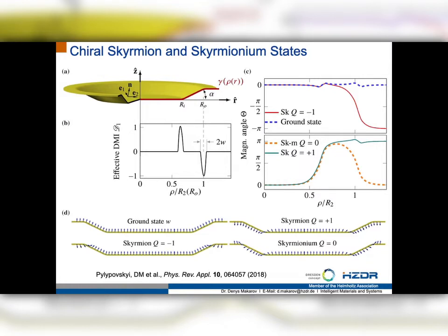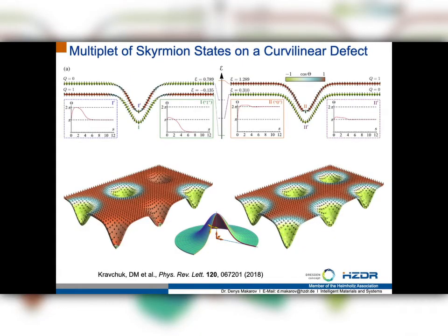You can go one step further and, for example, reduce the flat central region basically to a point. You will transform your plate-like geometry to, let's say, a Gaussian geometry. And this system is very special because you will have the possibility to create the external, larger domain wall, which is pinned at the band, which we discussed before. This is some kind of Skyrmion bubble, if you want. At the apex of the Gaussian bump, you will be able to create a Skyrmion of a very small radius. It's a curvature-induced Skyrmion due to the Dzyaloshinskii-Moriya interaction, so it has all properties of the standard Skyrmions which you have in chiral materials, like you know it from asymmetric cobalt sandwiches.